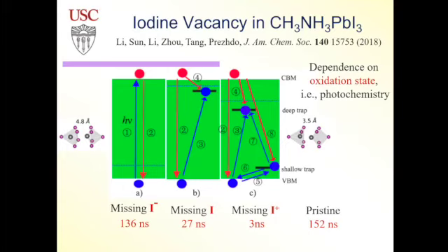When the distance shortens because of that, you create a new chemical species and you have many mid-gap trap states, which can be pretty bad. So if you make a solar cell and you characterize it with low light irradiation, you see everything works fine. But if you shine a lot of light, you send many charges, the whole chemistry changes, mid-gap states appear, and the properties of the solar cell change a lot.